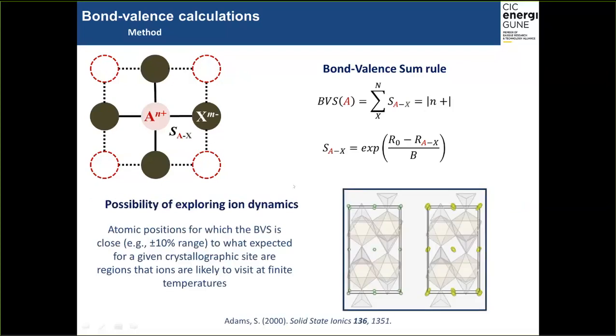So one key observation here is that the atomic positions for which the bond-valence sum is close, let's say within a 10% range, to what is expected for a given crystallographic site, are regions that the ions are likely to visit at finite temperature. So this opens the possibility to roughly visualize migration paths considering bond-valence energy landscapes.